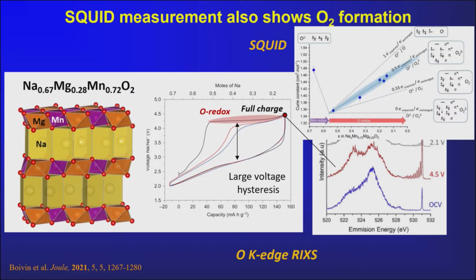Now, the dotted lines represent the predicted Curie constants, the magnetic moments that you expect evolving, depending on the nature of the oxygen species that you form when you oxidize oxide ions. And of course, there's no change if you go from oxide ions to peroxide, because they're both diamagnetic. There are no unpaired spins. And then those are the other species there.